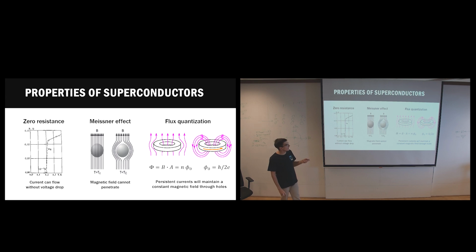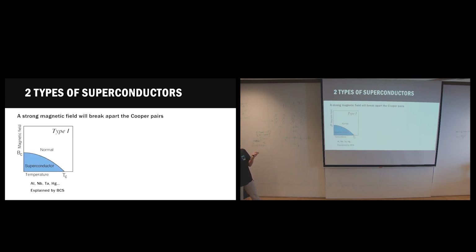And this is what we call persistent current. If I now turn off my magnetic field completely, it still cannot change. The field inside cannot change, right? So the superconductor will take care to generate a current that keeps one flux quantum in the interior. So the superconductor itself became somehow like a magnet now. And this current will flow forever, or at least, when they started doing these experiments, I don't know, 30 years ago, the current is still there. So persistent is a good name.